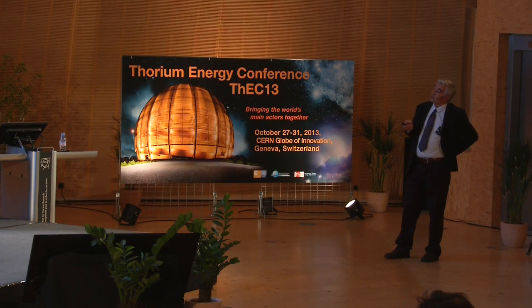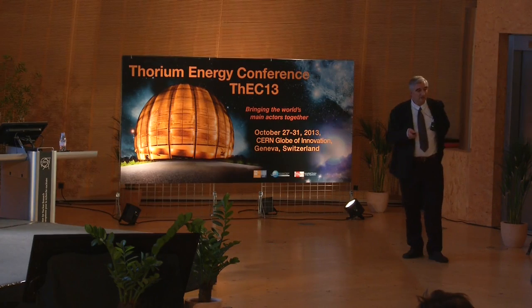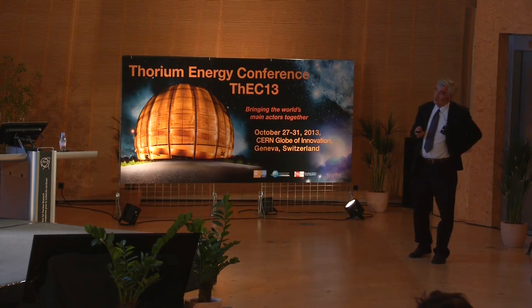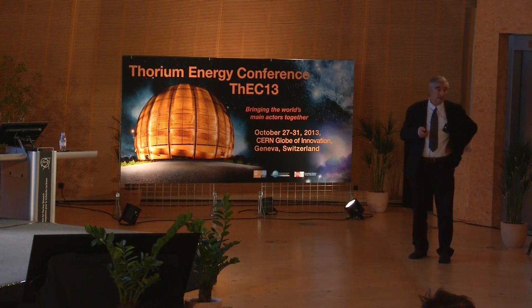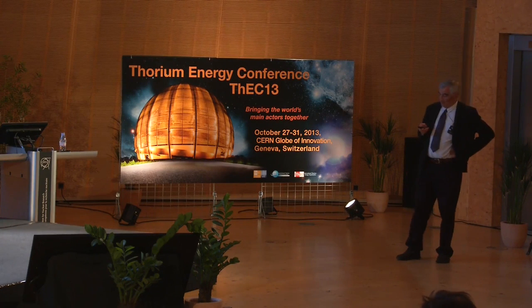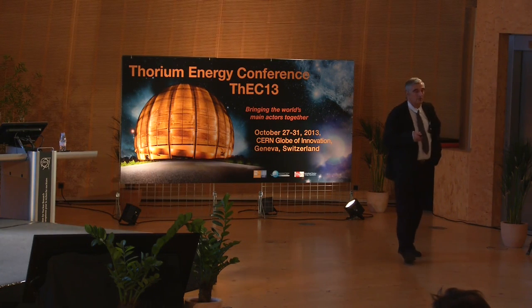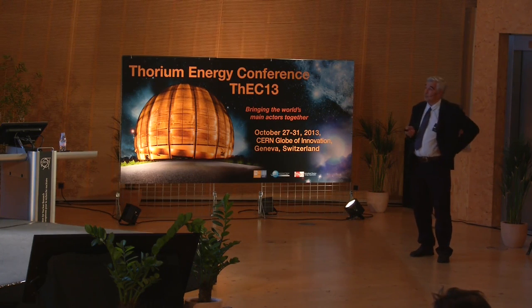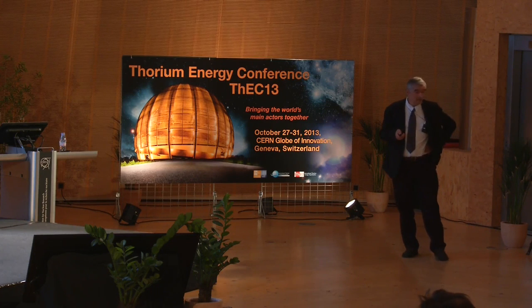Okay, the feedback from integral test, I don't go into much detail, but there was a very important step before installing the target in front of the proton beam. It was tested in the real conditions with a dedicated heater at the bottom in order to see different points. Of course, to establish the procedures for LBE filling and draining operations, checking the operability of main components of the target, check and calibrate the instrumentation, determine the thermohydraulics characteristics of the system, simulate heat deposition with the heater, obtain the vital parameters for system control. This is very important because we anticipate the fact that there would be some trips, and it was necessary to check that the control systems were able to mitigate the effect of these phenomena.